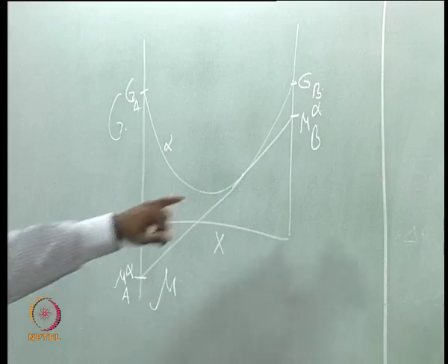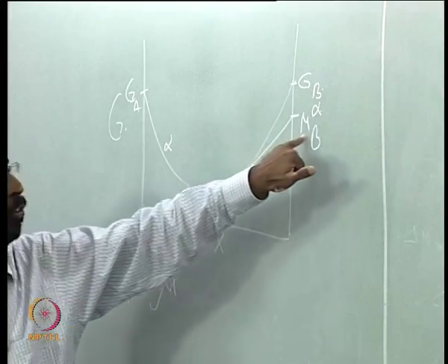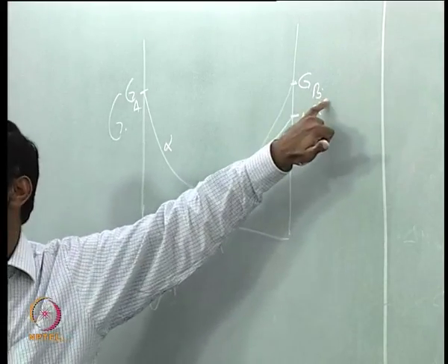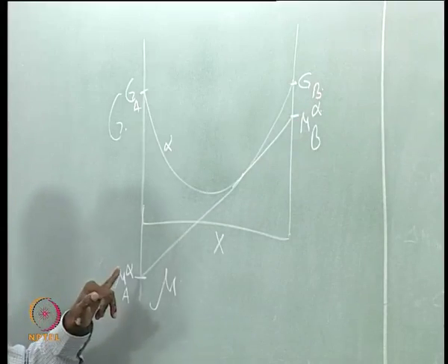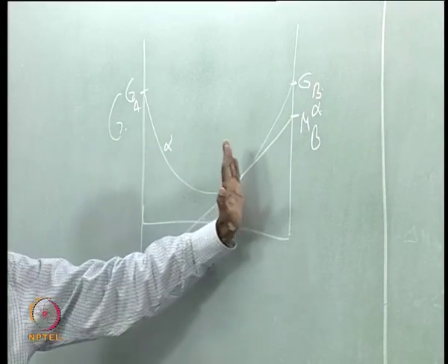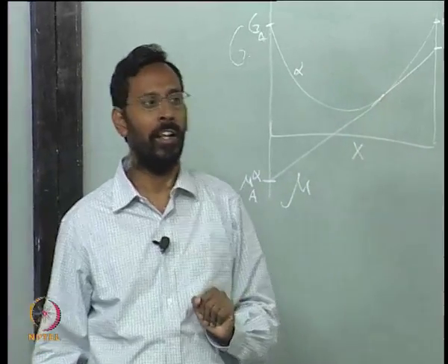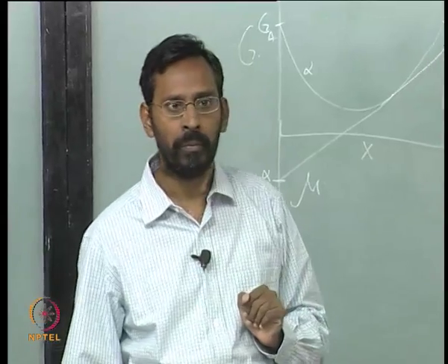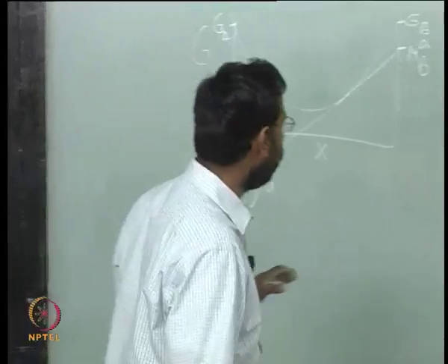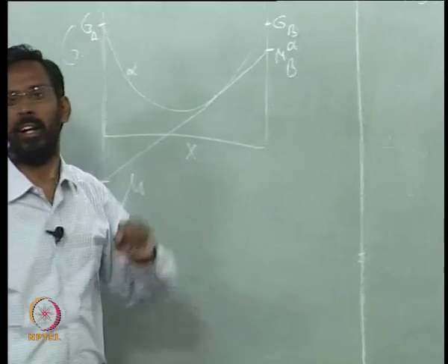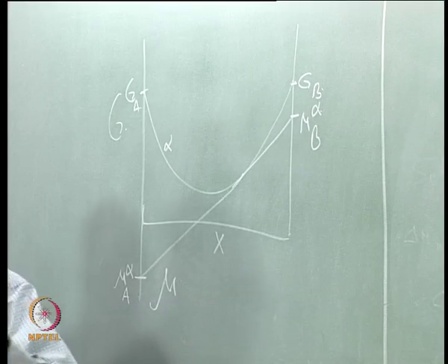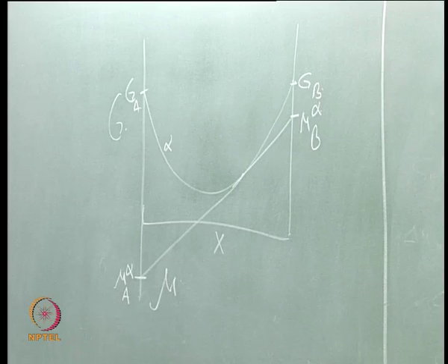Here, for example, if I show you that mu B in alpha is higher than mu A in alpha, I can say that for that composition at that temperature, B atoms are more active in alpha than A atoms. So, activity and chemical potential are directly related, and this is what we are going to use to understand what is called the equilibrium between two phases.